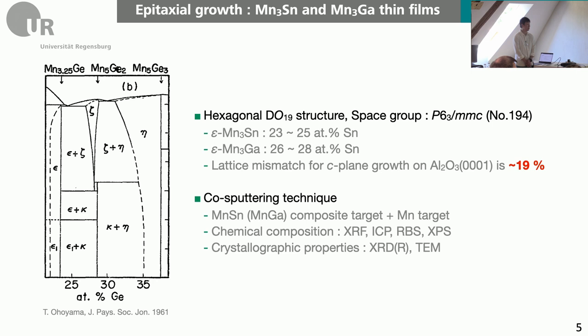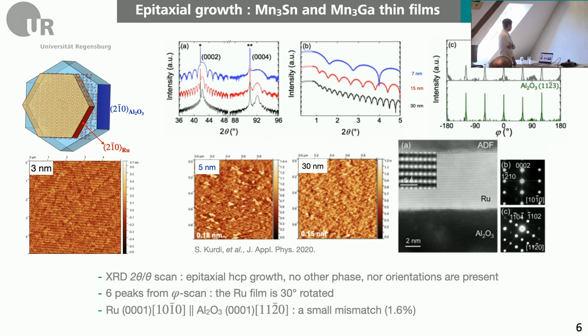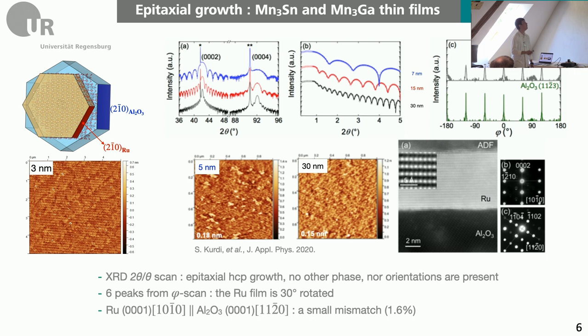Let's begin with the ruthenium buffer layer. As I said, it provides the proper foundation for manganese-3-tin and gallium to be grown on top of the substrate. We achieved a really nice and smooth surface of ruthenium, and we checked the orientation — the relative orientation of ruthenium with respect to certain axes of aluminum oxide. We found that the ruthenium film was grown 30 degrees away with respect to the A axis of the aluminum oxide.